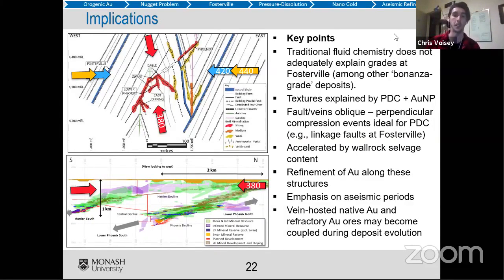So we explain this process with pressure dissolution creep and gold nanoparticles. Faults and veins that are oblique or perpendicular to a principal compression event, so the linkage faults at Fosterville, are ideal for this pressure dissolution creep mechanism. And then the amount of wall rock you have in it will increase it. So if you have a bunch of wall rock selvages in a vein, then you can have a lot more pressure dissolution fronts to remove more material from it. And you're going to have gold refinement along these structures. You'll remove the decaying material, leave the good stuff.